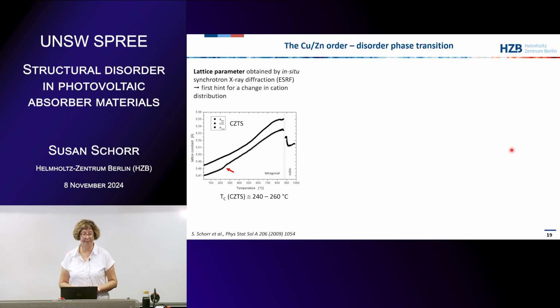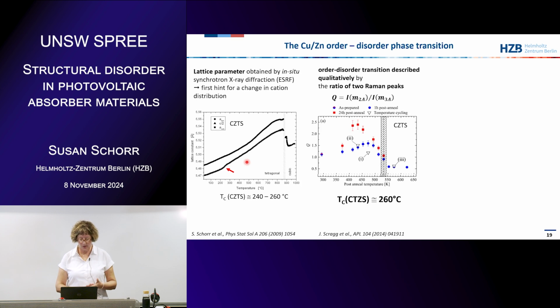Then I also did experiments at the European synchrotron facility in Grenoble to study high temperature phase transitions in kesterites. This is copper zinc tin sulfide, lattice parameters a and c half in dependence on temperature. And you see here this little step, which I could not interpret from the synchrotron data, because these are X-rays, so I could not distinguish between copper and zinc. I just guessed in that publication that it's maybe a change in the cation distribution. Later on, this paper from Jonathan Scragg came out, and he asked me, "Oh, Susan, you have seen such a bump. Could that be a change in the cation distribution?" I said, "Yeah, maybe, I don't know, it's synchrotron X-rays."